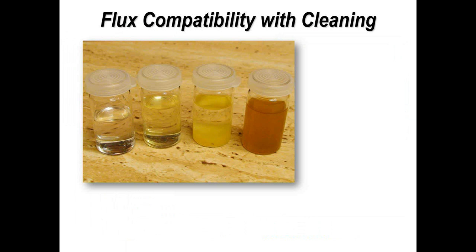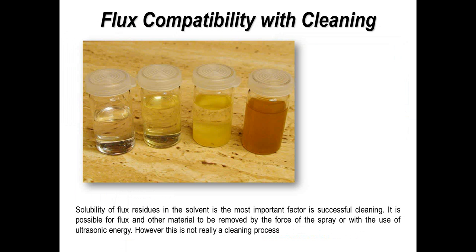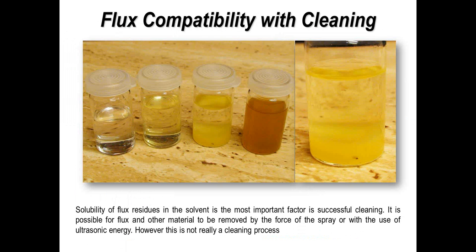If we step back briefly and talk about cleaning, one of the key things that a lot of people don't consider thoroughly is the compatibility of the soils you want to remove from a printed circuit board — it must be compatible with your chosen cleaning product. Here we have a visual representation of fluid being contaminated with flux, going from clear to rather dark material. As the solids content builds up in the cleaning solution, it changes color. The important thing is to make sure that whatever process you're using, the material is truly soluble.